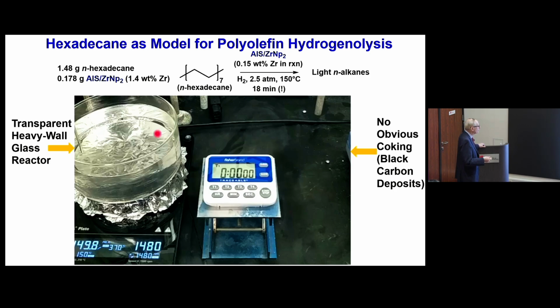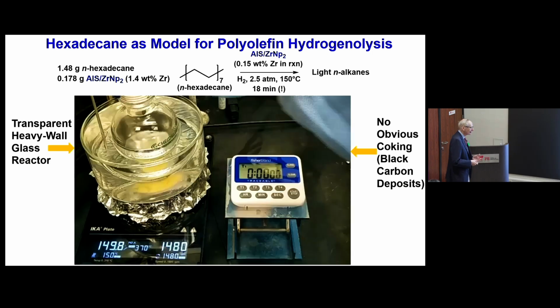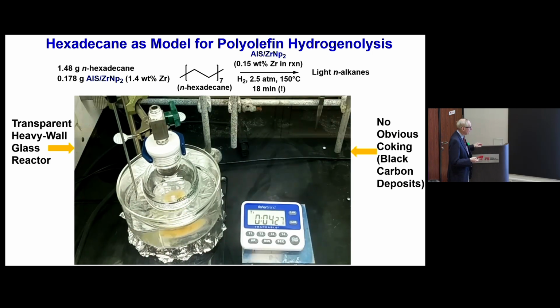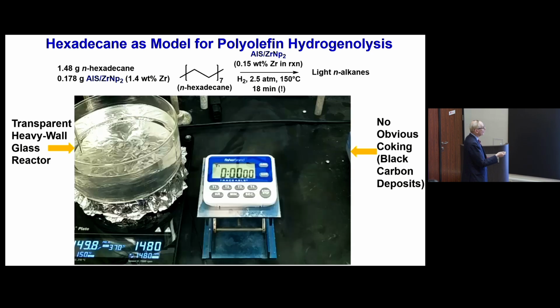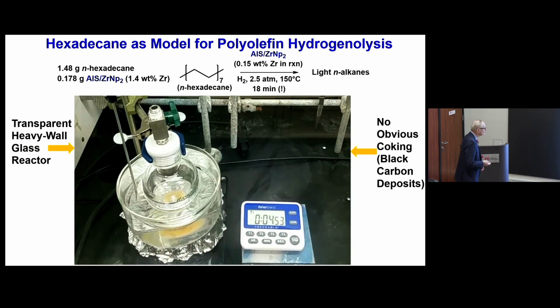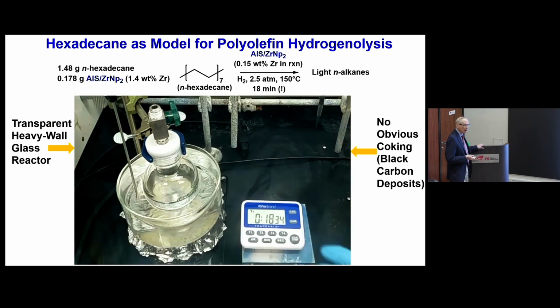Now this is a hot plate with oil in it. So oops, sorry, let's go back. I don't want to break the, so this is the reaction then. You're going to see a white powder, and that's the catalyst, immersed in a liquid, hexadecane. We're going to stir at pretty low hydrogen pressures and low temperature, and watch. And this is showing the time. The hexadecane is completely gone under these very, very mild conditions. I'll do it once more just so you can see.